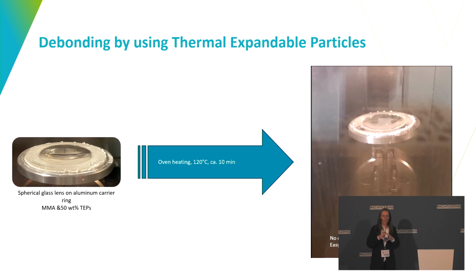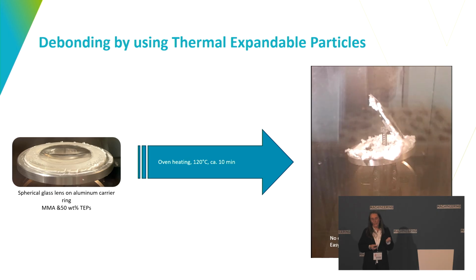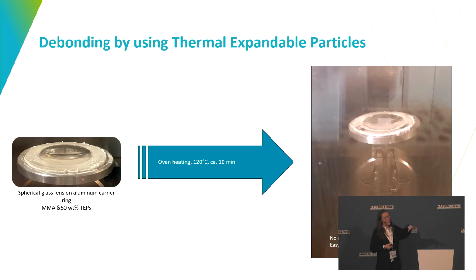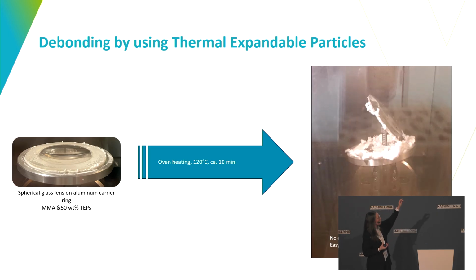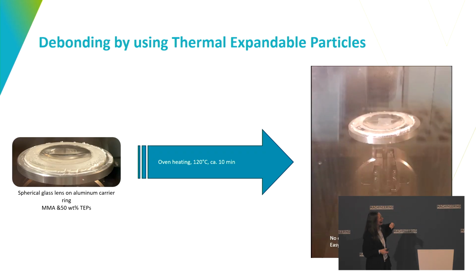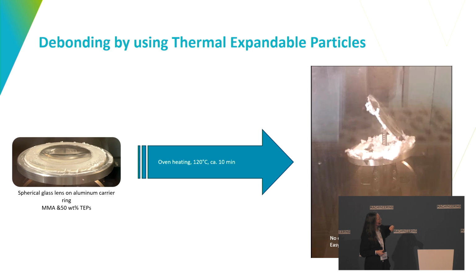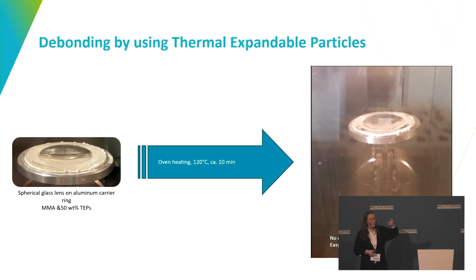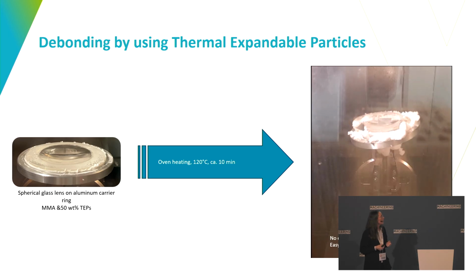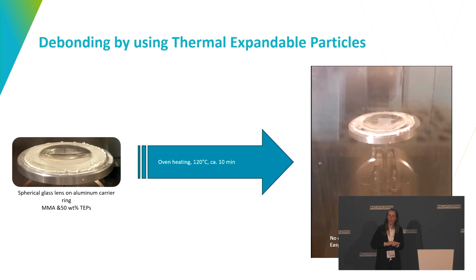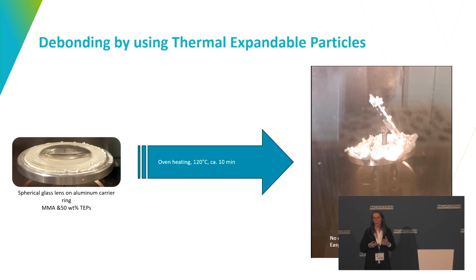When we put the complete product in an oven at around 120 degrees, within less than 10 minutes, as you see appearing on the video, everything is debonded. The product is just put on a certain mount, and it is just its own weight that is debonding the complete product. You see that the adhesive is being foamed up due to the particles inside it. It's a brittle residue on the substrates that can be erased quite easily, and both of the components, without any damage, can be prepared again for a new adhesive bonding if we want to. Also here, there was a risk, of course, that your glass and your aluminum have too high a difference in thermal expansion, that there would be too much tension on the glass and that cracks would occur, but this is not the case.